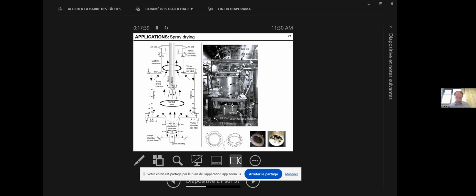Yeah, those in the center, you need to contact efficiently the hot air with droplets. So you want a high droplet concentration. So we use 4 nozzles in parallel. We developed a sleeve, a protecting sleeve, a bit similar to what they use in commercial spray dryers. In order to prevent fouling, we inject some secondary air through this sleeve to keep our nozzles clean.